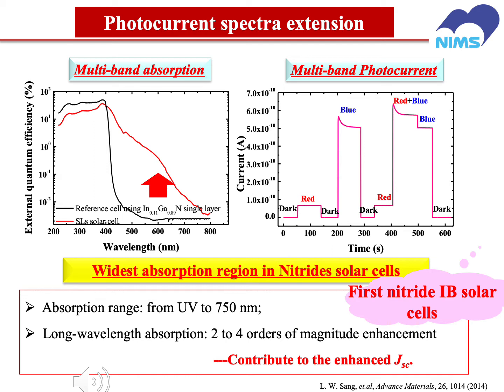And this figure shows the multiband photocurrent. So here we can see that if we use the two beam light illumination, the red light and the blue light, the photocurrent is the sum of each light's photocurrent. So this also confirmed the existence of the multiband photocurrent.